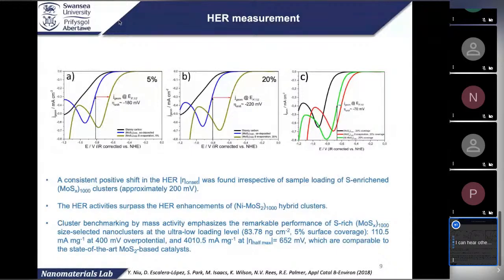And from both A and B, you can see there's significant improvement regarding the onset potential. For the 5% one, you have 180 millivolts saved, and for the 20%, you have 220 millivolts. And the thing is, if you calculate the exchange current density, compared with the pure MoS2, the nickel-doped MoS2 has exchange current density 30 times higher than the pure MoS2.